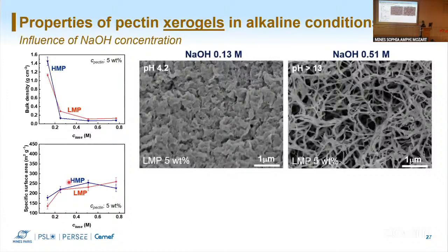We can see the structure again. So in this case, when we have very, very high bulk density, we can see the structure of our material that is very dense. We cannot really see the porosity. And when we go to high base concentration, we get a very nice structure. Not as nice as acidic pH maybe, but we have very open pores and well-defined fibrils. And you can see the dashed lines here are the properties of the aerogel materials. So when we're in high base concentration, the dashed lines that are the properties of the aerogel materials are almost overlapping. So when we're in high base concentration, the properties that we get by evaporation and by supercritical drying are very, very similar.